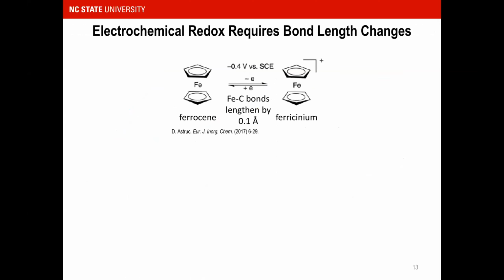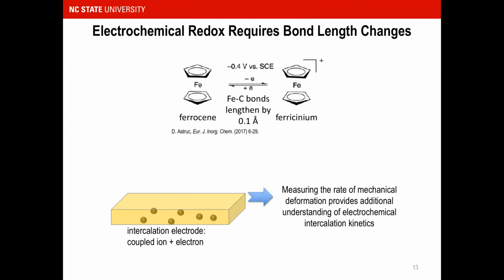So when we wanted to understand why this was happening, we wanted to take a look at how electrochemical redox affects the bond length changes. And if you have a very simple molecule like ferrocene, when it's oxidized, it will have a lengthening of its iron-carbon bonds by about 0.1 angstroms. So then imagine if this happens to an intercalation electrode like the one before, you have all of these tungsten cations accepting electrons, you have cations and protons coming in. The material is going to expand in volume. And so measuring that rate could provide additional understanding of electrochemical intercalation kinetics.